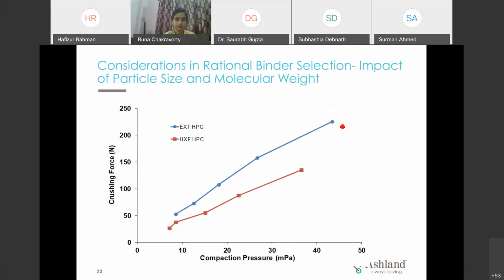Coming to different molecular weights, as we discussed earlier, Klucel is available in different molecular weights. We have a low molecular weight grade and a high molecular weight grade. Which one should you recommend? As I mentioned, we recommend using the lower molecular weight binder. This is what we have done. We made a tablet using 5% concentration of binder. In one batch we used Klucel EXF, and in another batch Klucel HXF, which is the high molecular weight grade. We compressed tablets at different compression forces, ranging from 5 megapascal to around 40 megapascal.